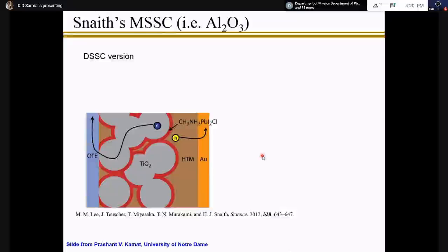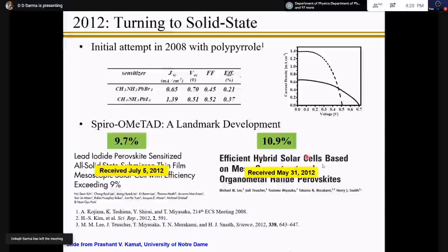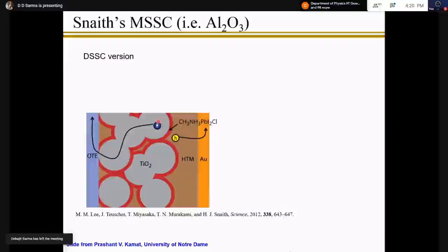The dye-sensitized solar cell that I talked about, which also was the structure that this paper from Michael Grätzel's group used, is basically a structure made of, let's say, a mesoporous structure of small particles of TiO2, which is coated by this material, in this case methylammonium lead iodide with a little bit of chlorine, for magical reasons that were not understood at that time. This is the absorber, and then a hole transporting material. So the photon would be absorbed in this material, which is very, very thin, because it doesn't have to conduct the electron and hole. The electron would jump into TiO2 because of band alignment, and the hole will jump into the hole transporting material. The electron will go through the TiO2 and come to the terminal, and on this side the hole will go to the other terminal, and externally you can connect it and get a current flowing through.